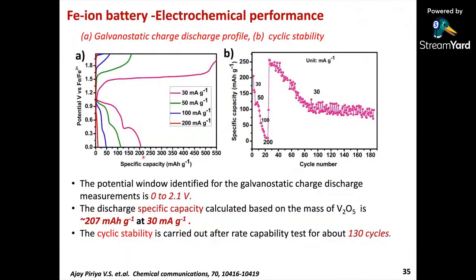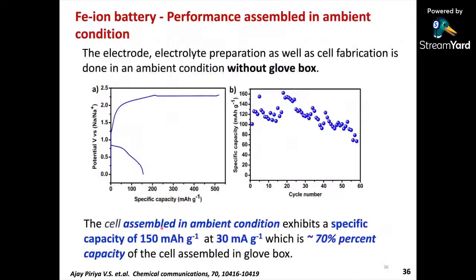And we could get a performance in the potential window of 0 to 2.1 volts and a specific capacity of around 200 milliampere hour per gram at some 30 milliampere per gram. And the most interesting thing is that we have done the entire assembly without any glove box, and we could get 150 milliampere hour per gram at 30 milliampere per gram current density.